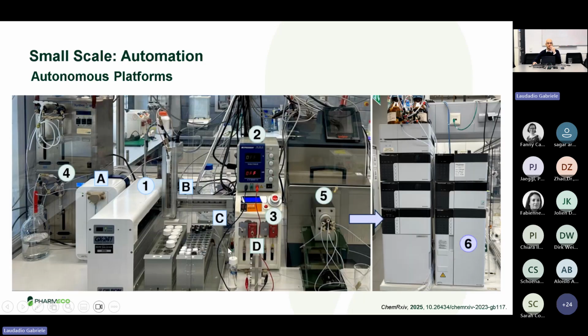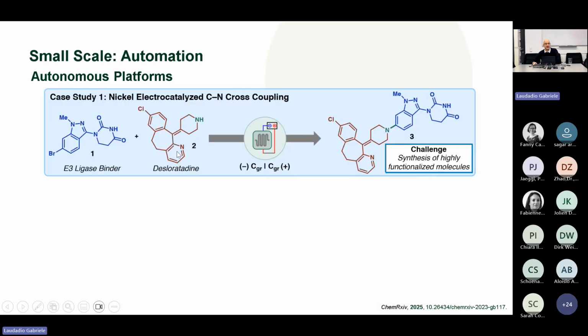It's very similar to the previous one. So we had basically the same liquid handler, the power supply, the pump, the reactor, and then we added a 6-way valve to compartmentalize the ambient pressure system to the high pressure that was going directly to the UPLC analysis. And in this case, we took over from where we left.